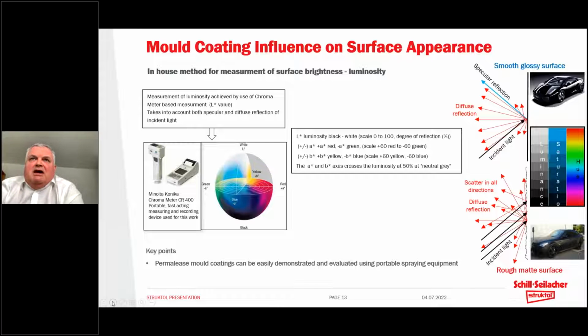So one very interesting aspect that we're working on, that we're developing, is the ability of a mold coating to influence the surface appearance of the rubber that's molded against that coating. One of the ways that we can measure this is to look at a value called luminosity. Luminosity is literally the brightness that we can measure. To do this, we would use a machine called a chromometer, and you see the portable handheld machine there. And we're measuring a 3-dimensional color space with the L value being the luminosity on a black to white scale, 0 to 100.